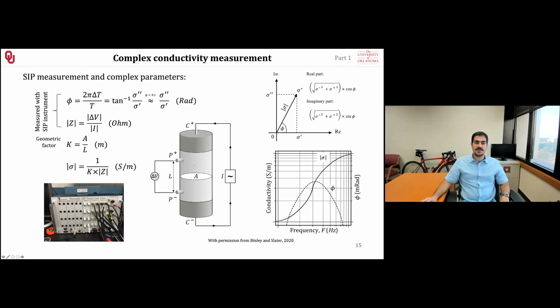Now, to convert this to real and imaginary part, we will use these two equations because it's a complex number. It has an imaginary part and a real part. The real part would be this equation: the square root of the squared real conductivity plus the squared imaginary conductivity, multiplied by the cosine of the phase lag. And the imaginary part is the same thing, the magnitude multiplied by the sine of the phase lag. So this is the imaginary part and this is the real part.